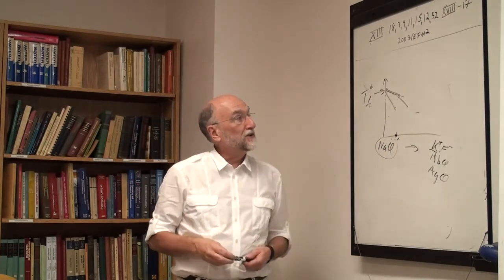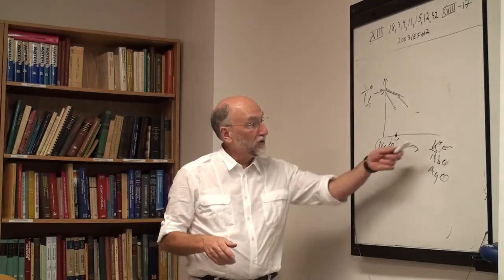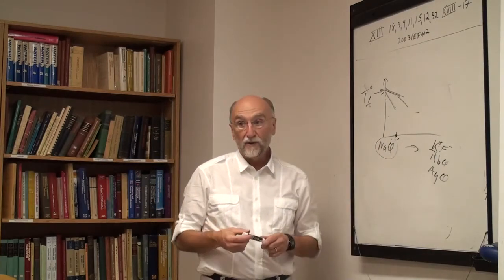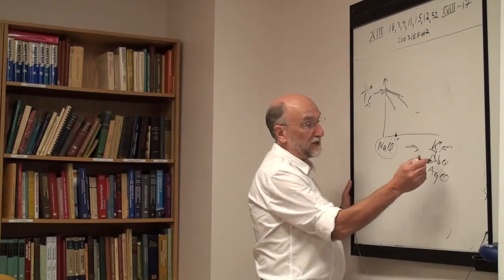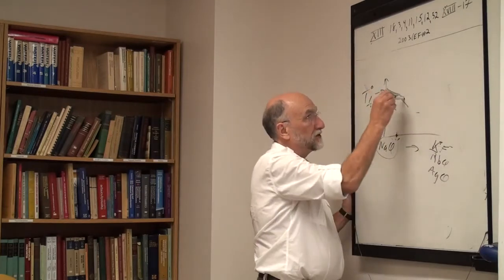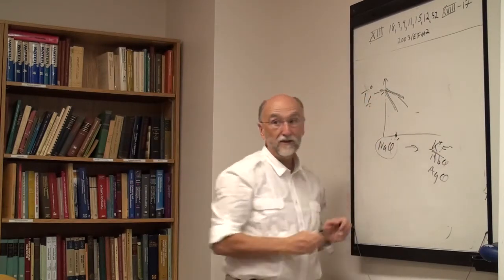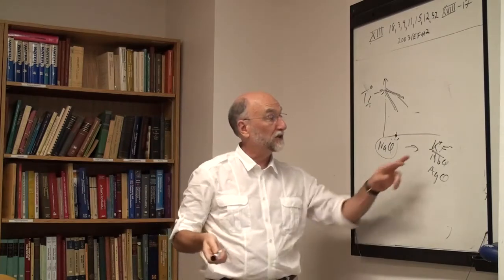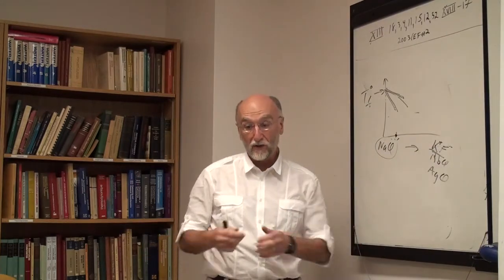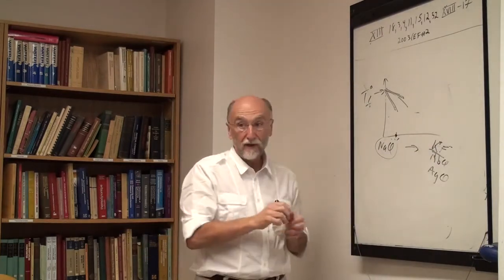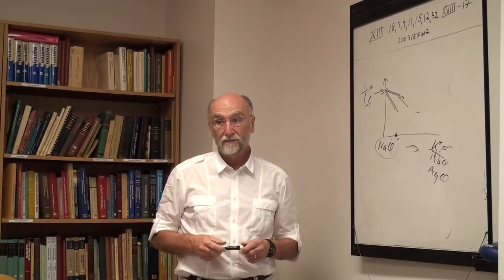In fact, this was the first evidence back in the 1940s that molten salts were in fact ionic liquids. And when they added potassium chloride, they got this slope. When they added potassium fluoride, they got exactly twice the slope, indicating for sure that the potassium and fluorine were dissociating. They weren't going in as a molecule, they were going in as 2 independent ions.